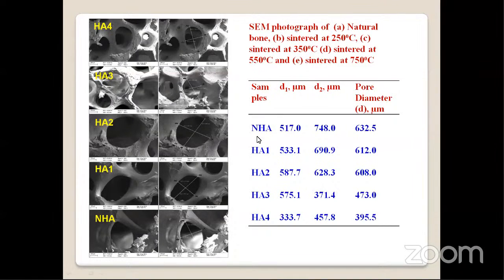See, the sample, natural hydroxyapatite, diameter. I have two cross-sectional lines in order to find the average diameter of these pores. Here, D1, D2 values, and the pore diameter is in the 632 micrometer range. When you are increasing the temperature, its size is reduced. 612. Again, 608. At 550, 473. At 750, 395. See here, when you are increasing the temperature, the pore size is getting reduced.